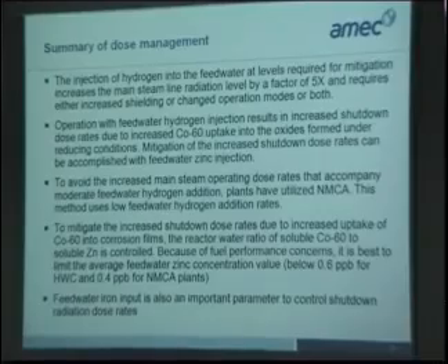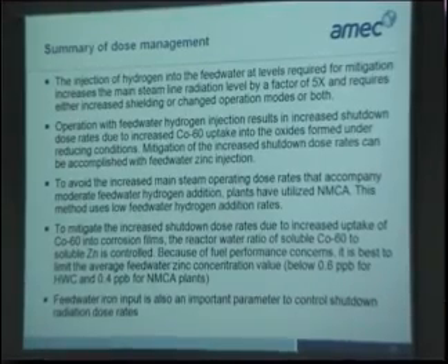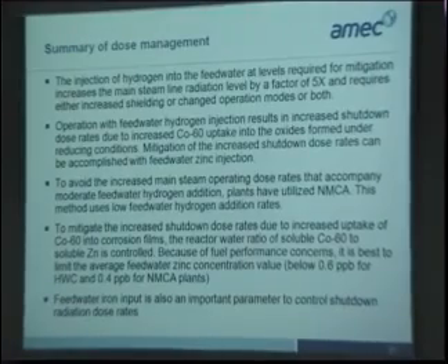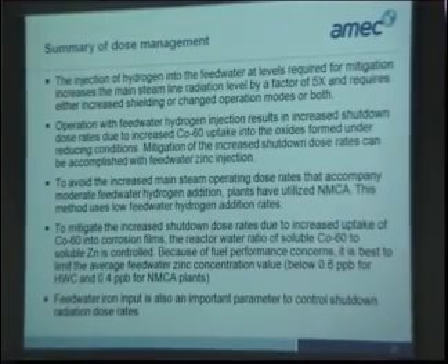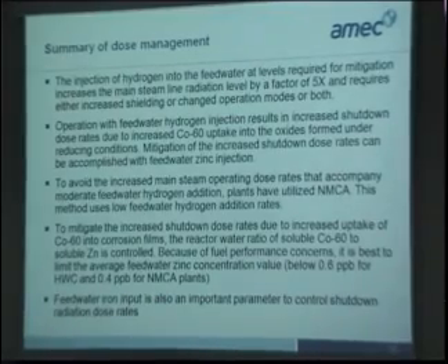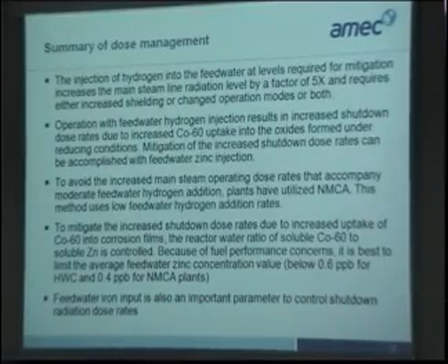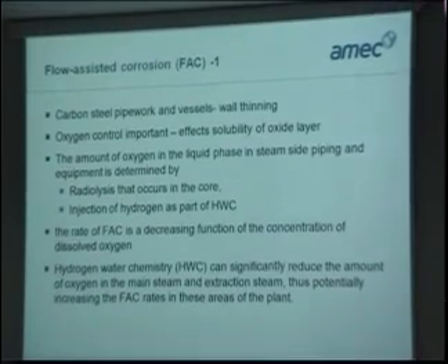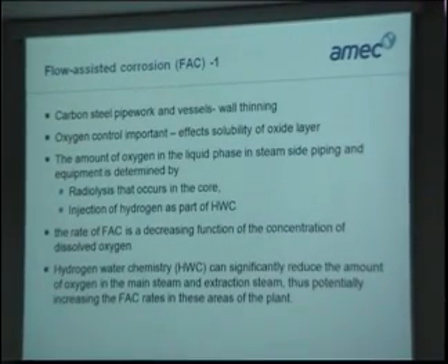So this really gives a summary of the dose management. Injection of hydrogen, operation with feed water hydrogen, controlling the shutdown dose rate effects, avoiding increased steam operating dose effects, for example using noble metal addition, using zinc to control the cobalt 60 in films, and controlling feed water iron. I'm going to quickly go through these slides because we are running out of time slightly.